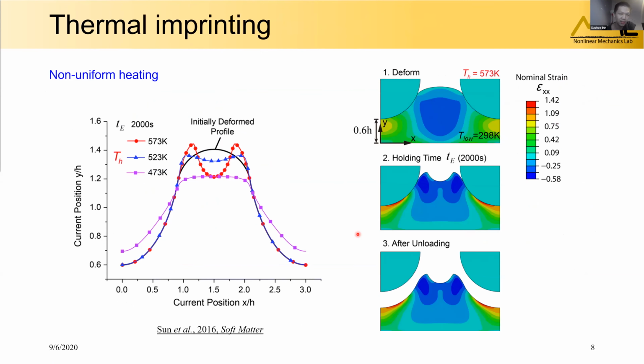There is another example for the thermal imprinting. We use a high temperature rigid indenter to press a low temperature Vitrimer substrate and hold the indenter for time TE and unload. The heat can be conducted from the indenter to the substrate and induce the stress relaxation. So an imprint can be finally obtained.